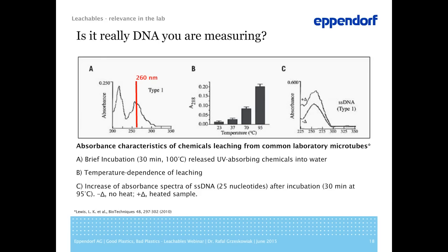So in panel A, on the left side, you see a perfect DNA spectrum with the distinct peak at 260 nanometers, which is actually merely a heterogeneous mixture of UV absorbing leachables from the lab tubes which were used in this experiment. The leaching process is temperature dependent, and as you see in panel B in the middle, extended incubations at higher temperatures will lead to more leaching and absorbance. And finally, as shown in panel C on the right, leaching may lead to a kind of false DNA amplification phenomenon, which is increasing DNA concentrations after heating the samples, as might be the case in PCR reactions, for example.